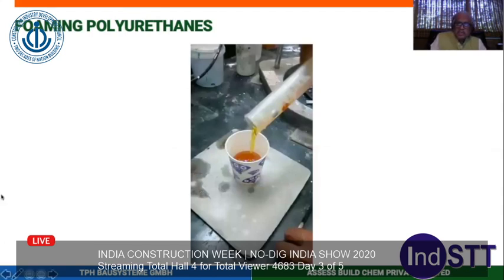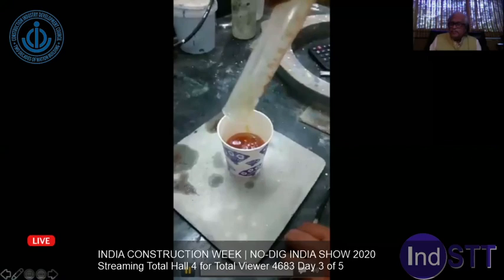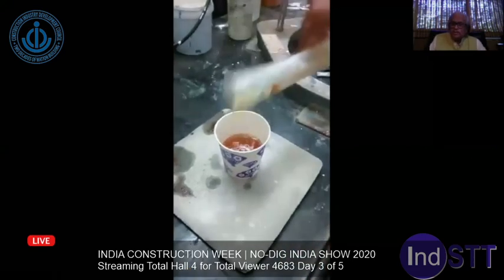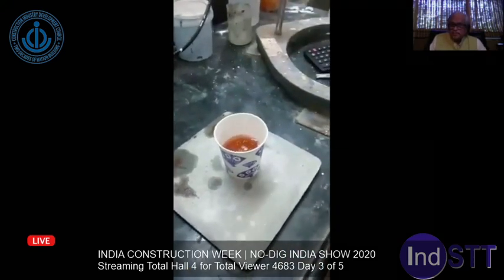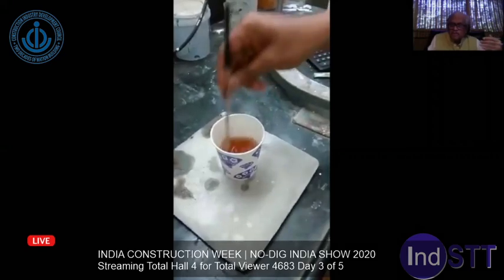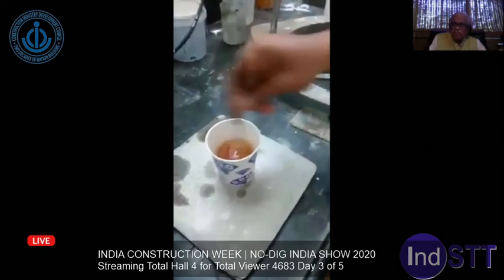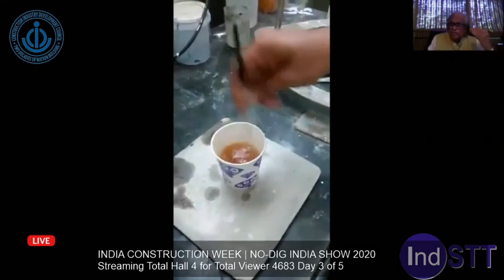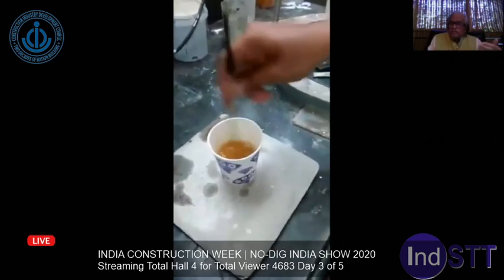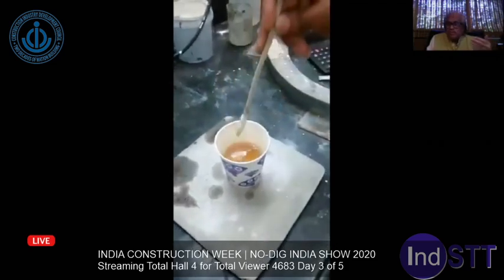Polyurethane foams are the basic thing, like one component foams, which are used for very low pressure injection. This is how it forms. The moment the material comes into contact with water, if you put a one component foam, it starts foaming. Now this is a very, very important thing that I'm saying. This can foam from 5% or from 3% up to 75%.